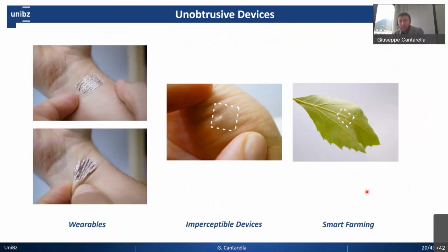Again, a motivation to make these electronics unobtrusive and highly transparent is what you see here. There are a lot of applications in the biomedical field, so for wearables or imperceptible devices. For example, these are devices that have been fabricated on PDMS substrate, and the use of indium tin oxide as metal contact, and then IGZO and aluminum oxide, which are already intrinsically transparent, give the result of a very imperceptible smart patch that could be placed on our body.